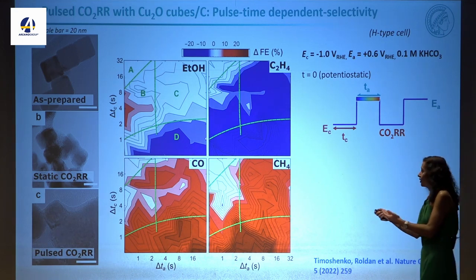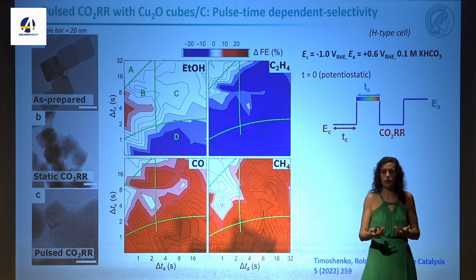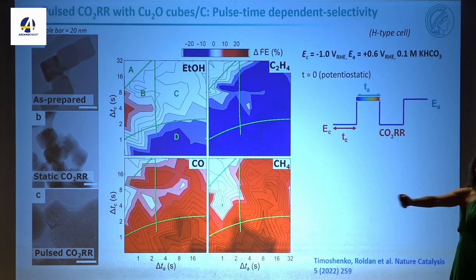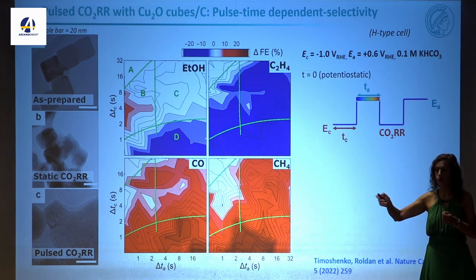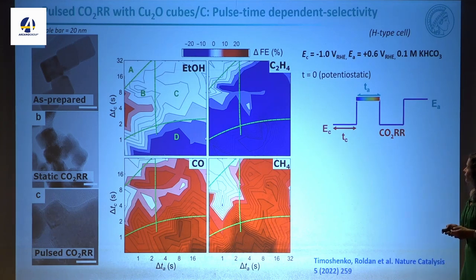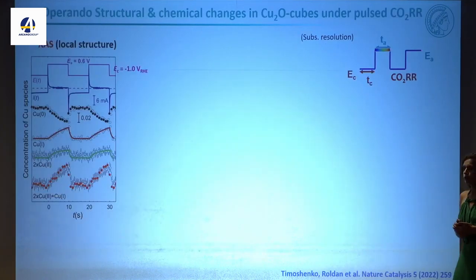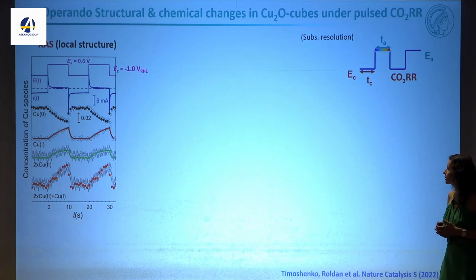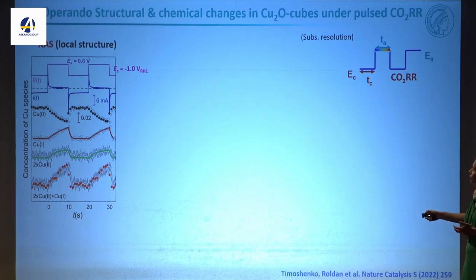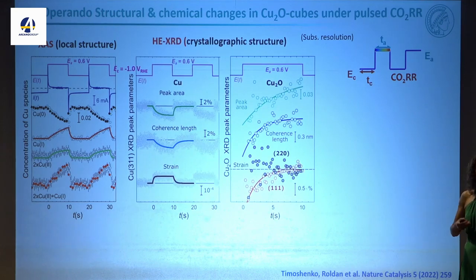So this is nice, and now I say, okay, how do I tune this catalyst? I know now, I apply the potential pulses, I get to the hardest product to get from CO2, ethanol, but what is the structure of my material? So now there is the possibility of combining different methods at the same time, and again, synchrotron measurements. These were done in Switzerland, combining X-ray absorption spectroscopy, which gives us information about the local structure, ordered and disordered phases, and also X-ray diffraction, which gives us information about the crystalline structures. And we have the possibility of doing quick measurements. Quick means sub-second resolution, even millisecond resolution.